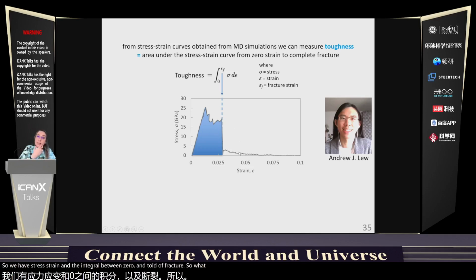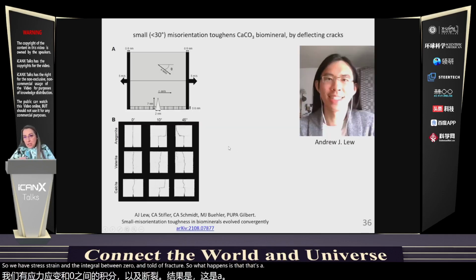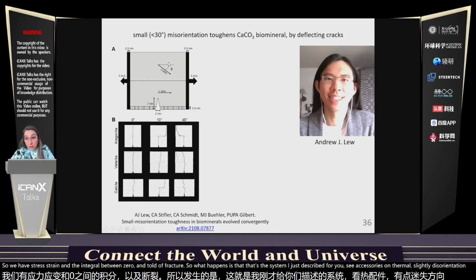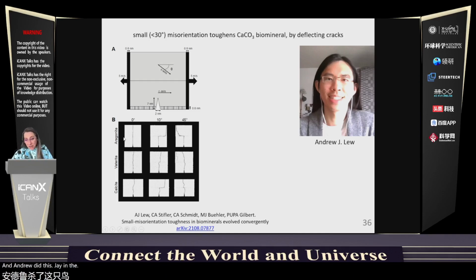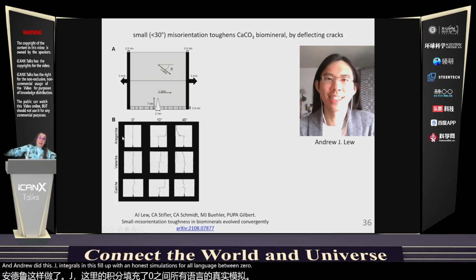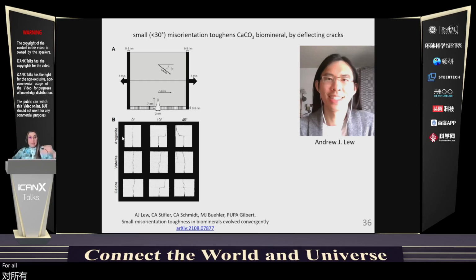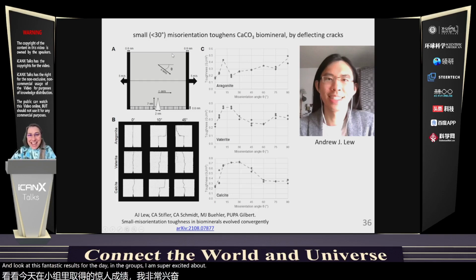So what happens is that's the system I just described to you, c-axis horizontal, slight misorientation or big misorientation, and Andrew did these J integrals in these molecular dynamics simulations for all angles between 0 and 90 degrees for all materials: aragonite, calcite, vaterite, and look at these fantastic results for the J integrals. I am super excited about this. Peaks at small misorientation angles for all of them.